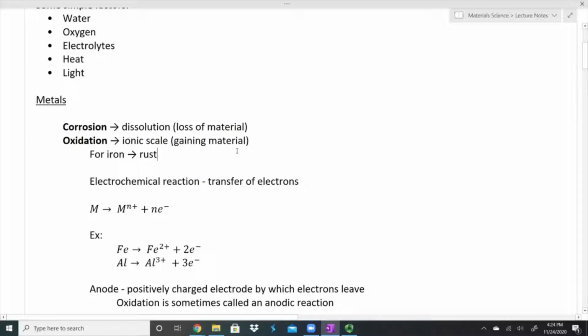So how come we usually don't get upset about leaving aluminum outside in the wet and in the rain and in the humidity? It's because the thin film of aluminum oxide isn't too bad. It's very hard, and it actually can end up protecting the material. It doesn't crack, it doesn't flake like rust does. Some other ones would be things like zinc oxide, and we'll get into that a little bit later as well.